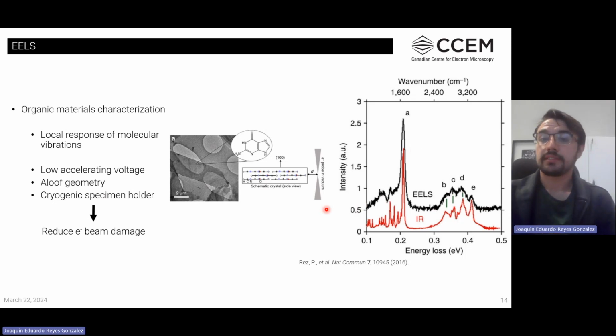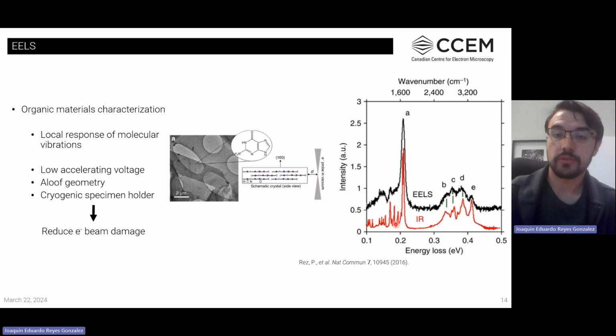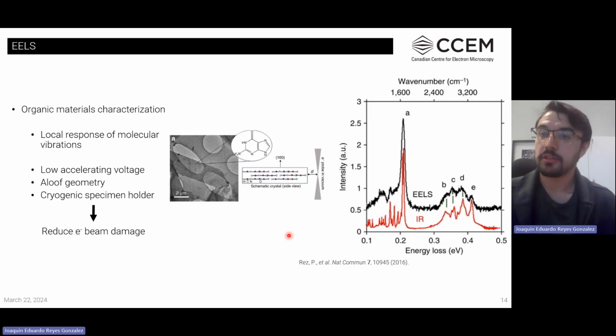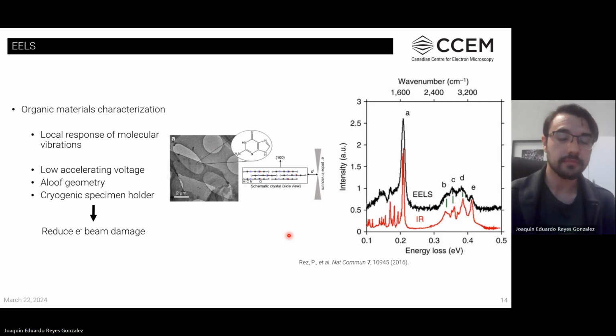When comparing it to an FTIR experiment, which corresponds to the red spectrum at the bottom, we can see that there is a lot of agreement between what the EELS can give you and what the FTIR can give you. FTIR has a higher energy resolution than what so far has been achieved with the electron microscope, but it lacks the spatial resolution that the electron microscope gives us, which makes it a very good complementary technique for the characterization of this kind of material.